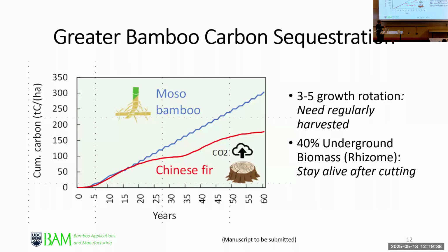And what's magic about bamboo is that when you harvest or cut bamboo, the rhizome actually stays alive. It does not die. Whereas when we fall a tree, the roots start to erode. And so you start to emit carbon dioxide right away. So that's the main difference. And also the other difference is obviously how fast it grows. And of course, the amount of underground biomass is substantial. Because the bamboo does not die, the plants stay alive after cutting, it makes bamboo cumulative during the whole rotation or harvesting process.